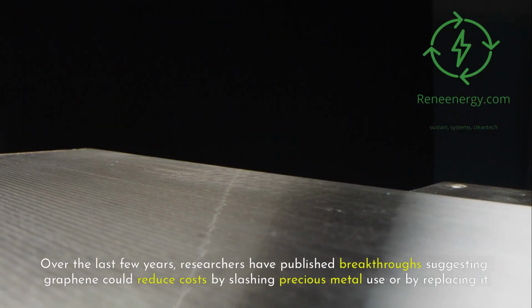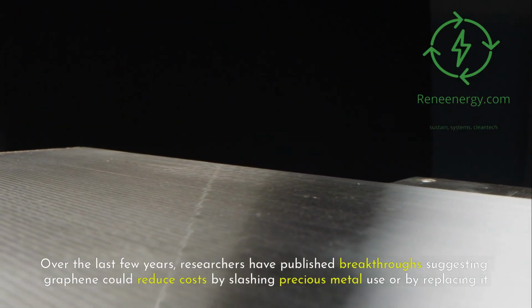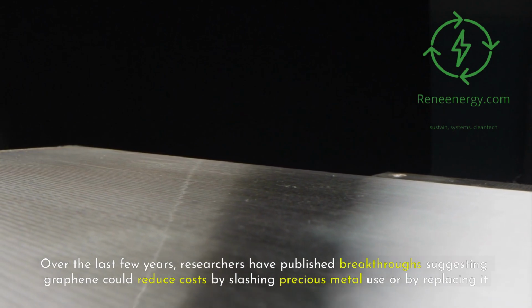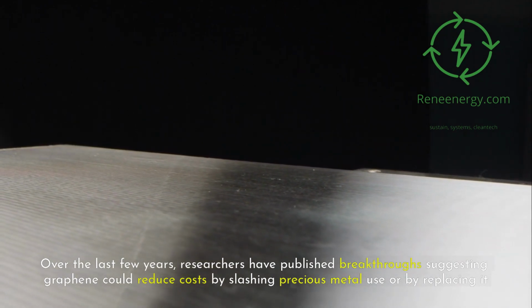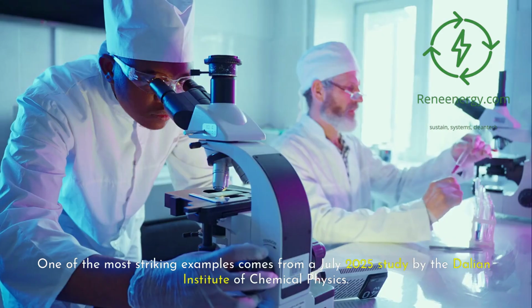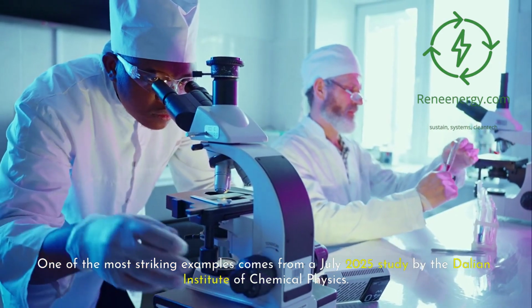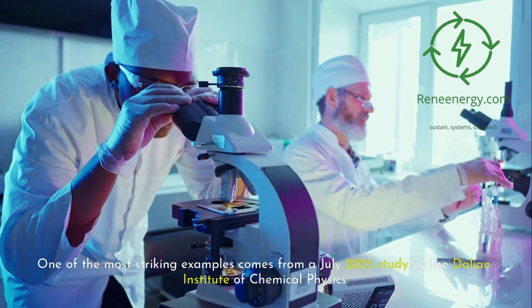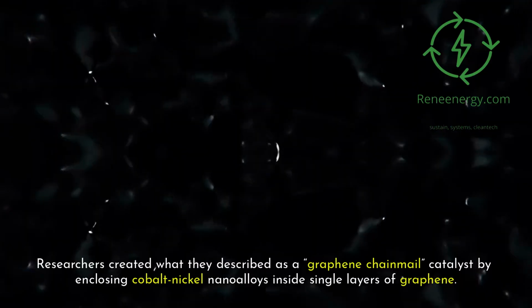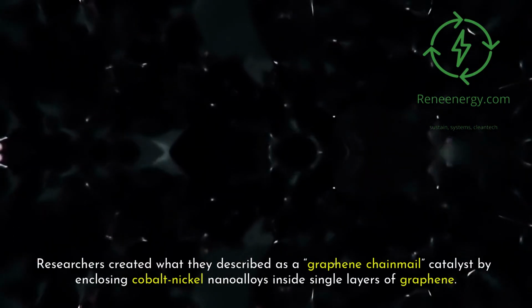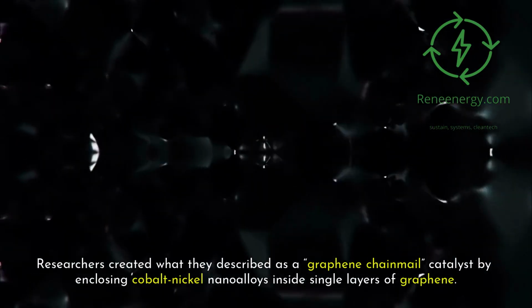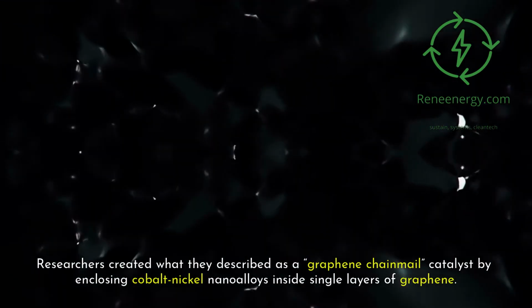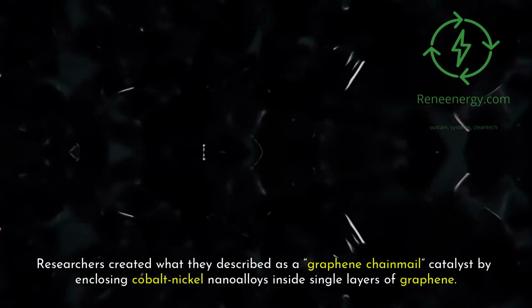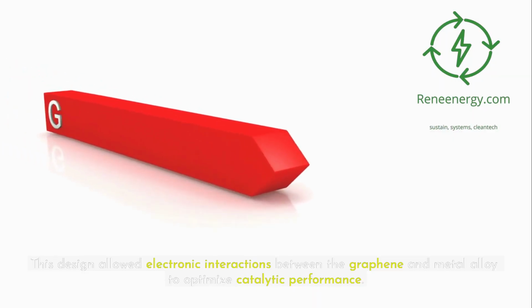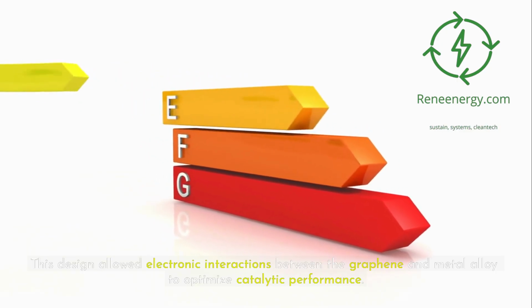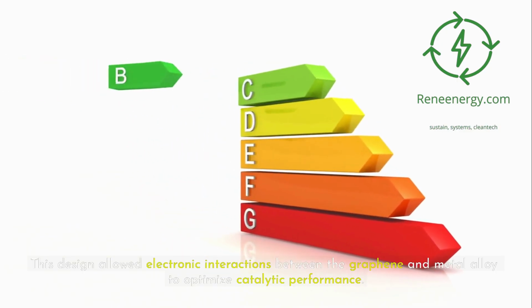Over the last few years, researchers have published breakthroughs suggesting graphene could reduce costs by slashing precious metal use or by replacing it altogether. One of the most striking examples comes from a July 2025 study by the Dalian Institute of Chemical Physics. Researchers created what they described as a graphene chainmail catalyst by enclosing cobalt-nickel nanoalloys inside single layers of graphene. This design allowed electronic interactions between the graphene and metal alloy to optimize catalytic performance.